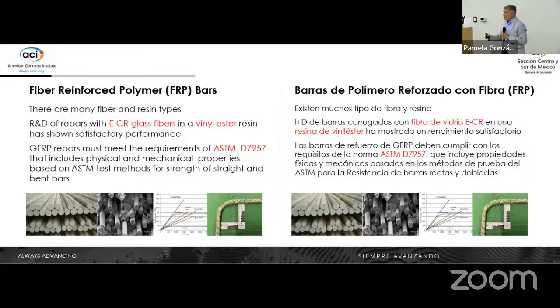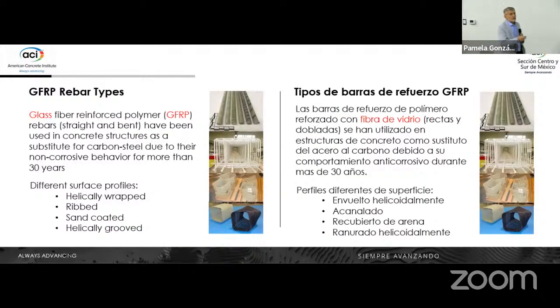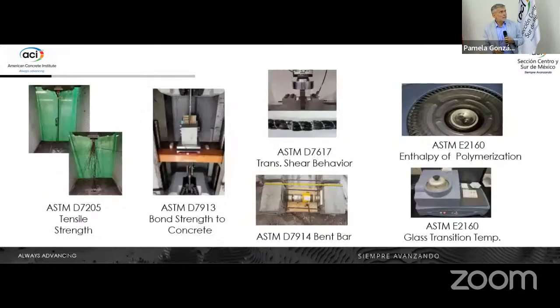So now we are blessed by the fact that we have a material spec, we have a code, and also we have another document that is 440.5, that is construction specification, material design code, construction specs. We have closed the circle. The bars kind of look different from the ones that you are familiar with. Depending on the supplier, they look different because these manufacturers have not standardized the surface configuration, but all these bars, if they are compliant with the ASTM D7957, provide adequate bond.